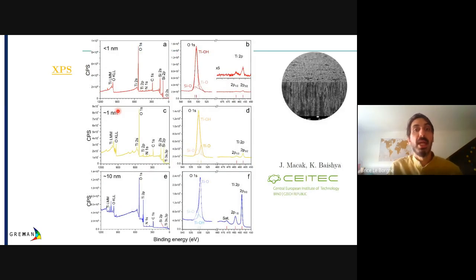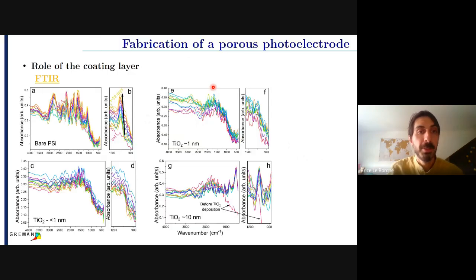Okay. And then to check if we were actually depositing on the porous silicon, because we couldn't see it by TEM or SEM, we performed, with CEITEC, so with Kaushik Baisha and Jan Matsak, XPS measurements on the thinnest layer, the middle one, and the thicker layer, which is still quite thin. And we observed we had indeed titanium dioxide even on the thin layer, so it was possible to deposit it. So that was really a success. And then we started checking for 29 days if it was actually oxidizing.